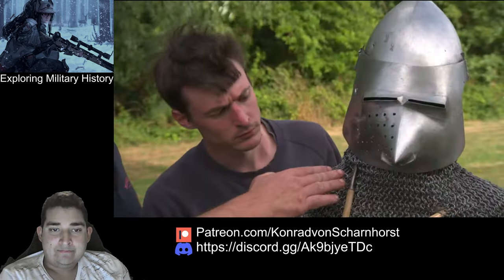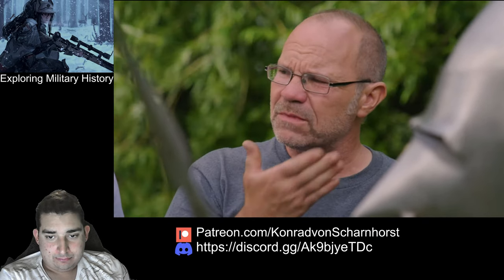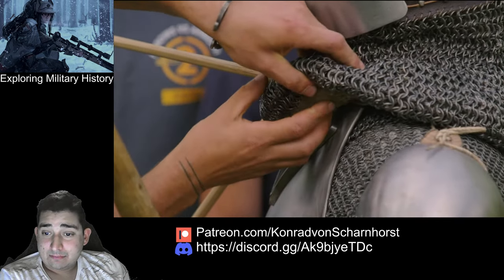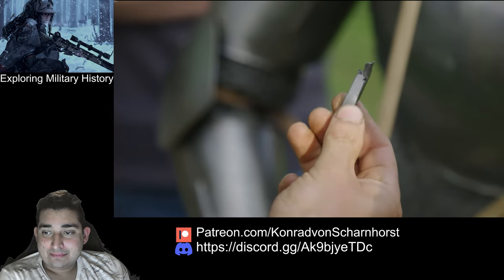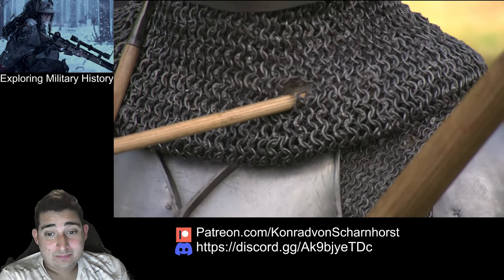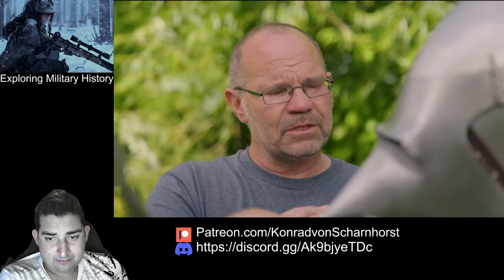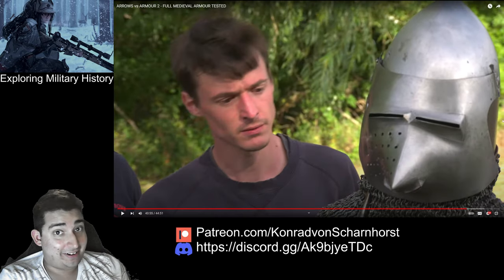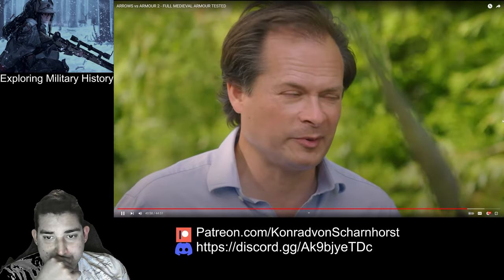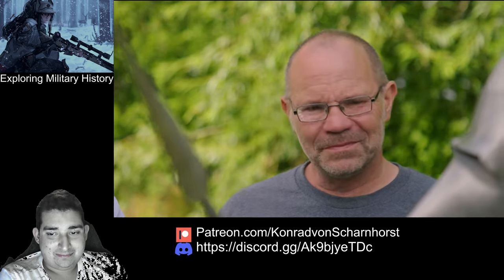If he was turned a little more towards the shooter, these are going through into dangerous areas — right around his throat — and that is a really delicate area to get punched. That's gone all the way through the aventail and out the other side — and it's pierced it at an angle, going through more of the material and more of the padding behind it than a straight hit would have. We really didn't think this aventail would be pierced — when you have it in your hands it seems so thick and dense and heavy.